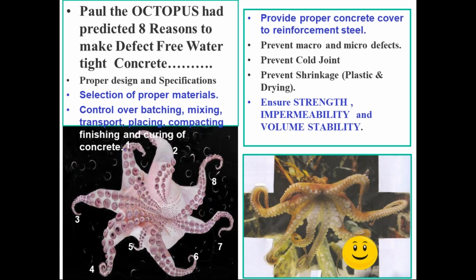So all these have to be executed properly. The next is provide proper concrete cover to reinforcements. Very important, so that corrosion does not take place. Prevent macro and micro defects in concrete. So excess water will dry out and cause problems of cracks and also the porosity, water cement ratio. All these things have to be avoided to avoid this defect.